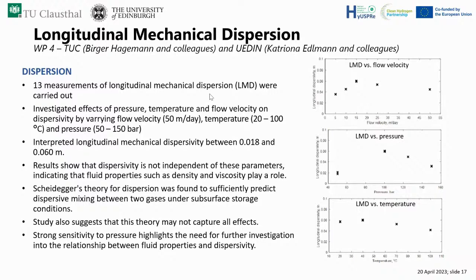Dispersion: also results from 13 measurements on longitudinal mechanical dispersion, investigating the effects of pressure, temperature, and flow velocity. Found that interpreted longitudinal mechanical dispersivity varies between 0.018 and 0.06. And clearly this dispersivity is not independent of these parameters. So fluid properties like density and viscosity definitely play a role in the dispersivity.